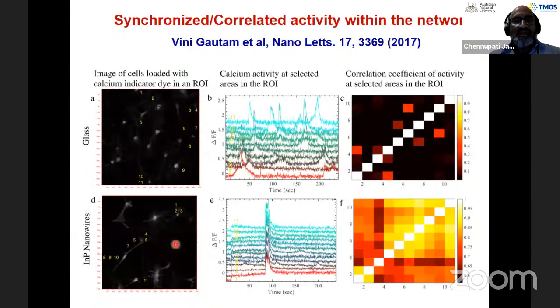So here's a case where the neurons on glass substrates show change in fluorescence as a function of time. You can see that the neurons grown on glass substrates are all firing randomly. There's no correlation taking place, and a very low correlation coefficient here. Whereas when the neurons are grown on indium phosphide nanowires, you can see the change in fluorescence as a function of time.